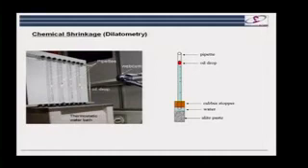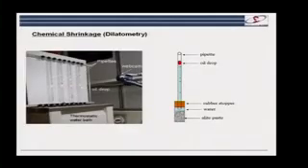So this technique has been available for a long, long time. Meta actually worked on this technique for her PhD. And the simple idea is that you have your paste in here, you fill it up, you have a little container here, you completely fill this with water, and then you have a capillary tube that's going up out of the sample, and as the paste is reacting here, the overall volume is going down, and to replace that volume, it sucks in water, and you follow that water being sucked in by this drop of oil on the top.